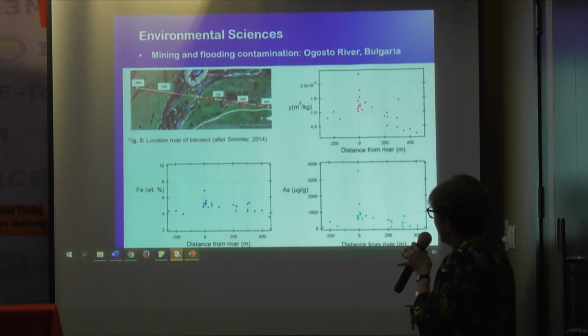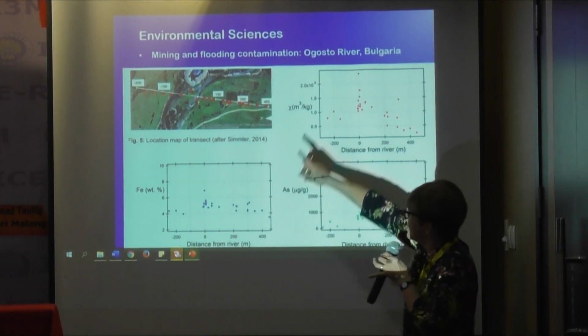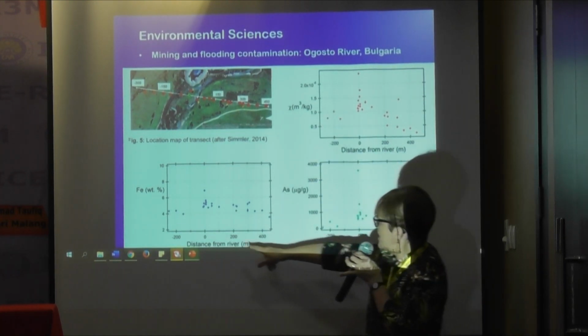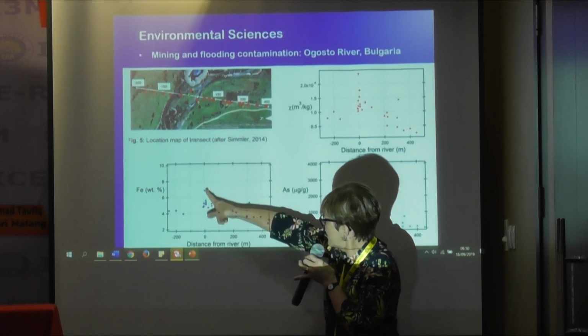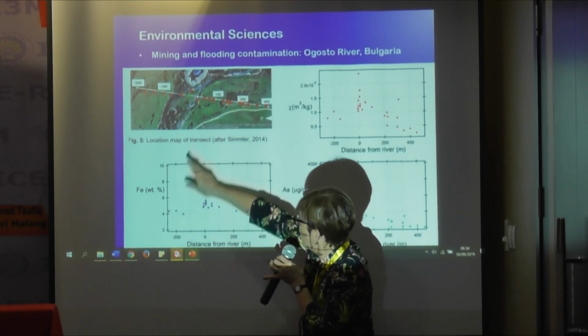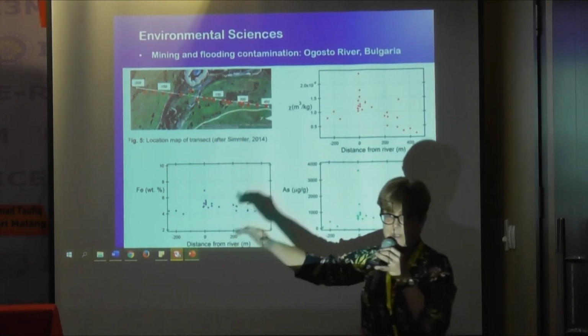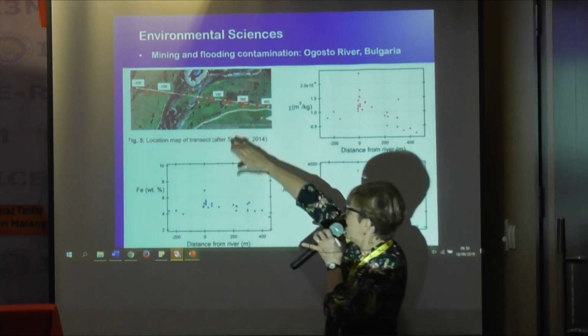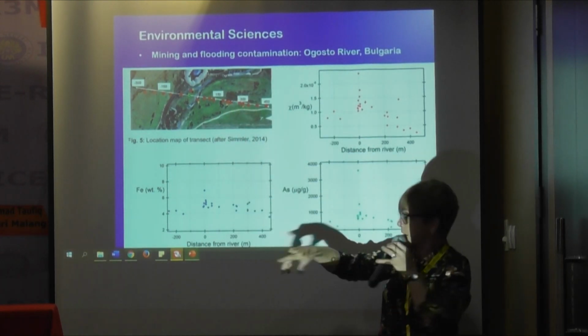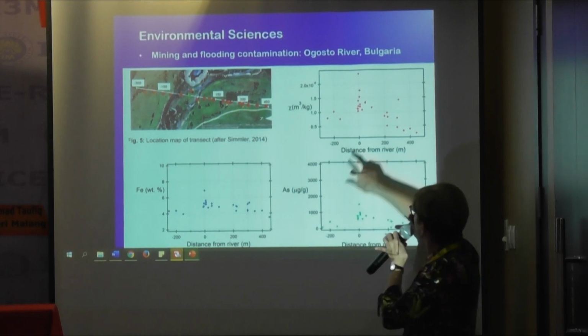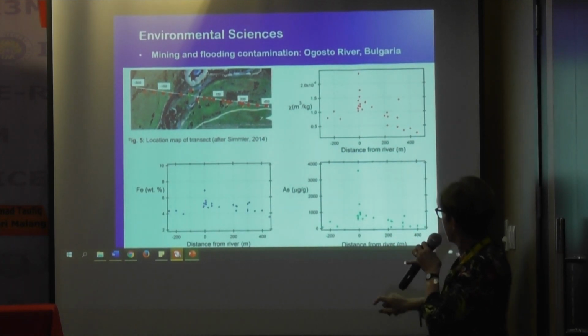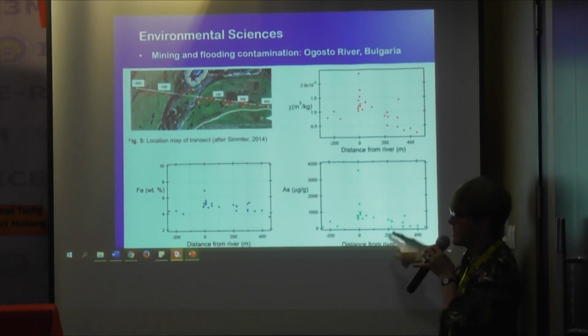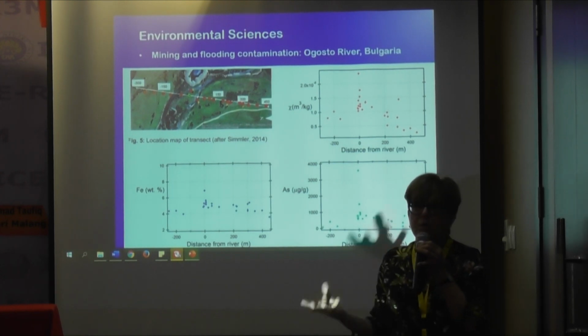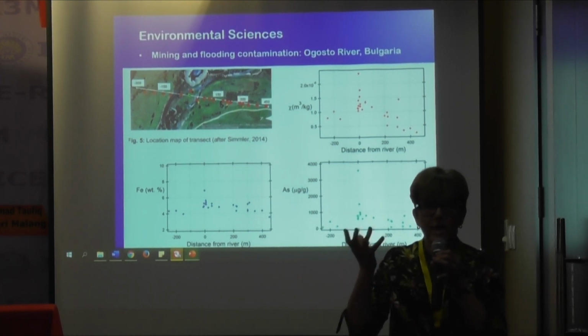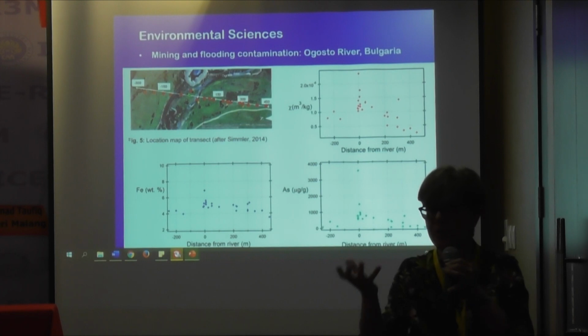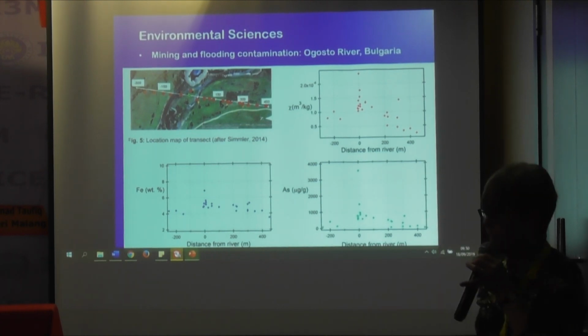Next. And then by doing profiles across the river, you can see iron peaks right at the river. It is lower on the upper side of the river where the land is a little bit higher. And on the lower side where you can get flooding, you do see a higher iron content, you see a higher arsenic content, and you can also see from the susceptibility a little bit higher. So the idea is they could then take more samples, measure susceptibility, and get an idea of the arsenic content.